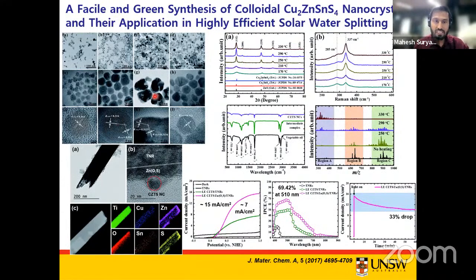The CZTS nanocrystals that we synthesized, we again sensitized just like in our previous approach. But this time, we sensitized these CZTS nanocrystals on TiO2 nanorod arrays, which were passivated with zinc oxysulfide layers. Just to let you know, we passivated the surface of these TiO2 nanorod arrays using atomic layer zinc oxysulfide. The reason is that TiO2 has surface defects, and passivation of those surface defects using zinc oxysulfide usually improves the performance of these TiO2 nanorod arrays. And then again, we loaded or decorated CZTS nanocrystals on this one, and we observed improved performance up to about 15 milliampere per centimeter square.